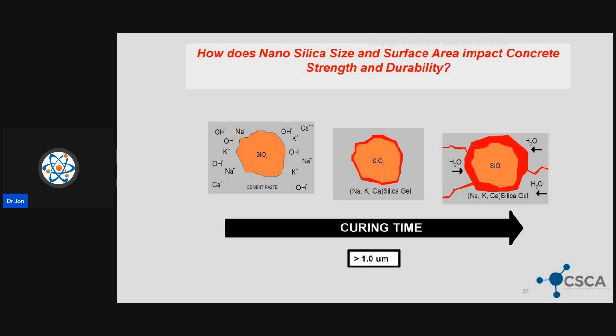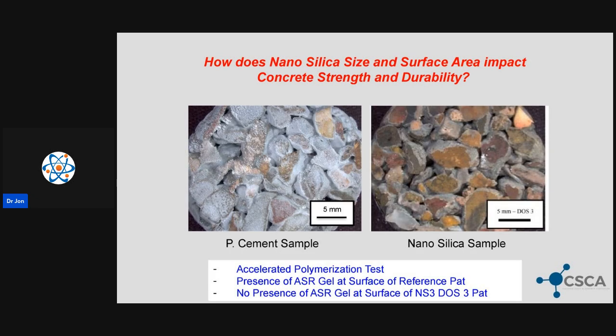Now, with our larger particles, they might not kick off that pozzolanic reaction as quickly, but what we found with those larger particles, 9 to 10, 45 to 47, even up to the 100 nanometer, is that we're creating a hydrogel that, even though it's not chemically incorporating into a calcium silicate hydrate network, is binding those alkalis that would then normally contribute to the ASR gel mechanisms that we talked about earlier and referred to in this image. Okay.